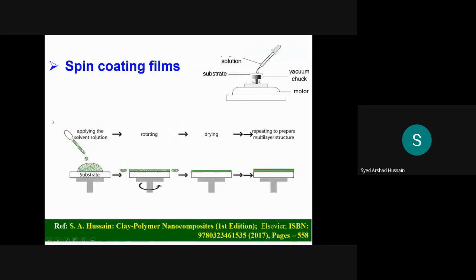And spin coating, you all know, we spread the mixture of the clay and dye systems on the substrate, and it's spun using a motor. It's of course fixed with a vacuum pump so that it does not go out. Based on the speed and time of rotation, one can get the film here. So it's a very simple process, but of course the control or preciseness of the thickness is not as well controlled as by the LB system.